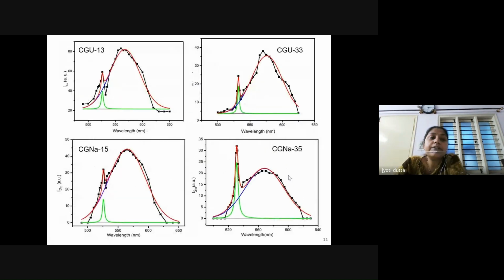Now we have observed that the same property was shown for all the four carbonaceous nanoparticles. For example, for 13 nanometer, for 33 nanometer, as well as 15 and 35 nanometer, in all the cases, what we have observed is the second harmonic peak is always associated with a broad multiphoton fluorescence background. The only difference that we can observe in these four nanoparticles is the contribution of the multiphoton fluorescence peak is lesser in 35 nanometer carbonaceous nanoparticles. Now, this is a matter of further investigation.